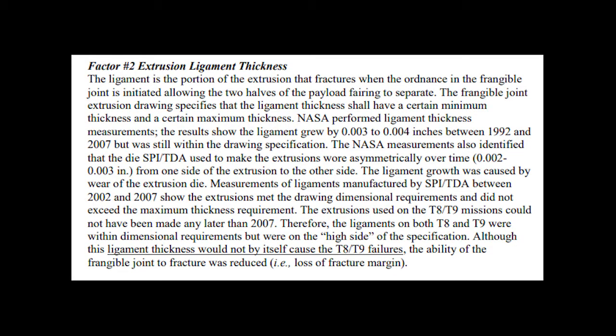The second reason given by NASA is that the ligament, which is the narrow part of a frangible joint meant to fracture, grew by between 0.003 and 0.004 inches between the time it was extruded and the time it was used. NASA claims that the die used to make the extrusions caused the extrusions to wear asymmetrically over time. However, measurements taken by NASA from 2002 to 2007 showed that the extrusions were still within the proper dimensions, although NASA claims they would have been on the high side. NASA also claims that these two factors contributed to the failure, but they alone were not the cause of the failure.